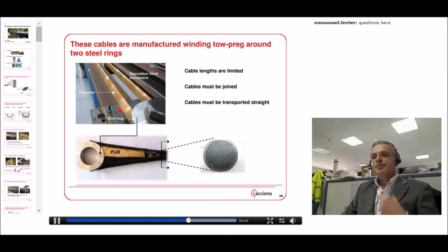Then you have 2 bands of FRP. The following step is that these 2 bands are wrapped with a thermo-shrinkable film. The film is heated up, so it shrinks, and you shape the cables. You give the cables this round shape. Close to the end, you insert a polyurethane wedge. Here there is a polyurethane wedge. And then you wrap carbon fiber around the cable core. You create a sort of carbon fiber sleeve for a certain length close to the end of the cable.